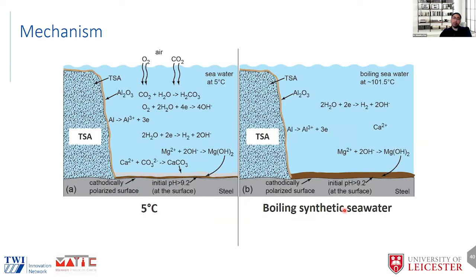And we looked at the mechanism in a bit more detail. In boiling seawater, because we don't have CO2 solubility, we are not seeing calcium carbonate formation. And at room temperature, we also looked.